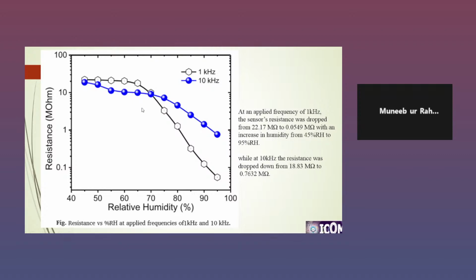If we increase the humidity beyond 65% RH, the resistance decreases abruptly. The reason is that when water molecules come to deposit, they adsorb in physisorption fashion. So the water layers are added up in the first, second, third, fourth and so on physisorbed layers. The H plus ion and OH ion are more mobile in the physisorbed layers, in the bulk liquid. So that is why the resistance of the device is abruptly decreased beyond 65% RH.